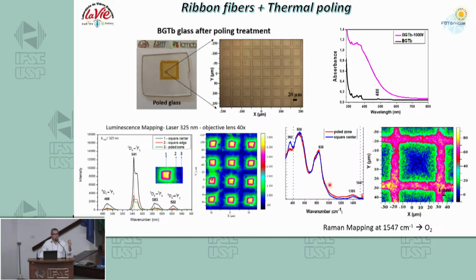And then we did the same using this electrode. And here, where the electrode, in fact, is here, where you send blue, there is no emission. So it's zero emission. And in the middle of the square, we have terbium 3. And here we have terbium 4. So there is no emission. So we can control where I can have emission in a device. So it's quite also nice.